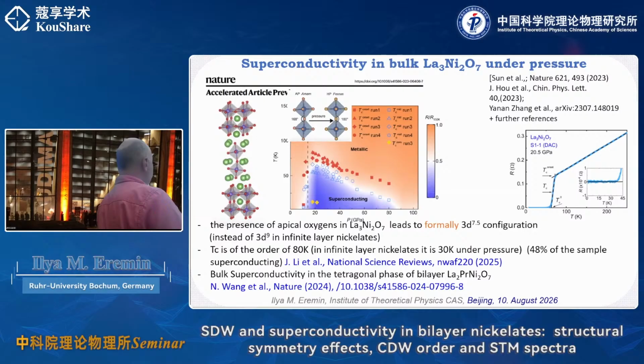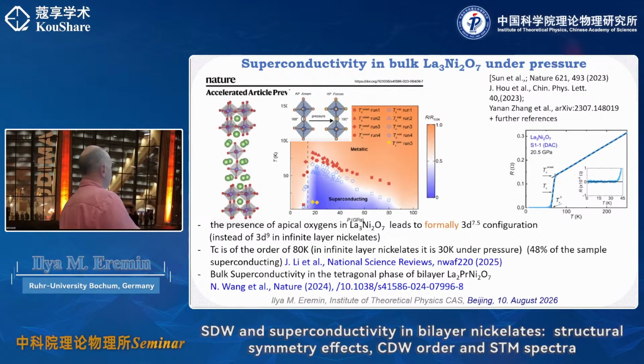And the primary reason from the crystallographic point of view why it becomes superconducting is that at ambient pressure the structure was claimed to be Amam. This again tells you that the field is very emergent, because I will show you a very recent slide. This is a representative of this. The most important part is that there is a tilting of the nickel-oxygen octahedra from one layer to another. If you apply pressure, there is a structural transition from the Amam to the Fmmm and later to the I4/mmm phase, which is a pure tetragonal state, because Fmmm is still orthorhombic, but I4/mmm shows zero resistivity.